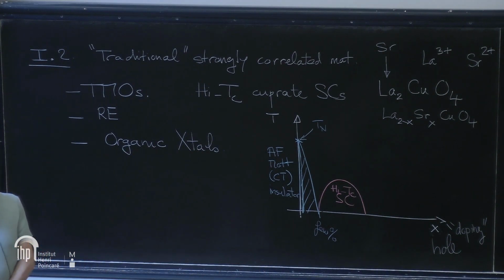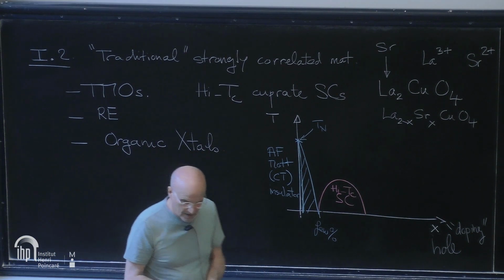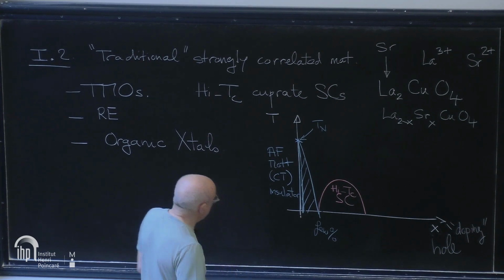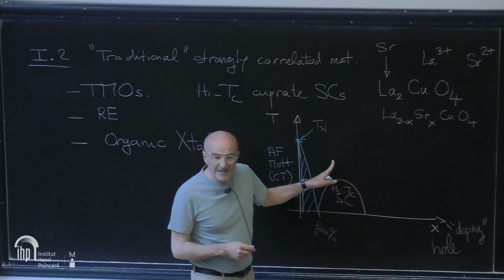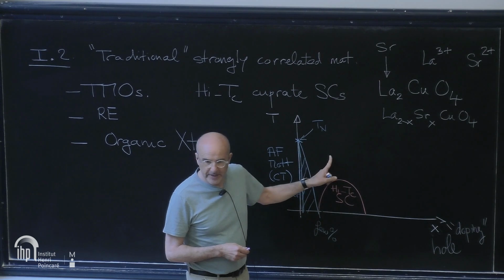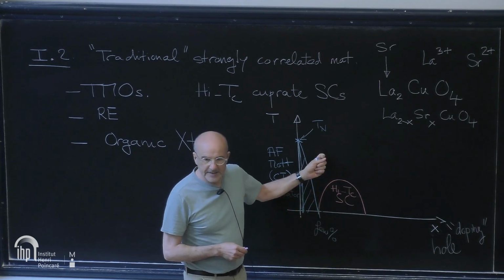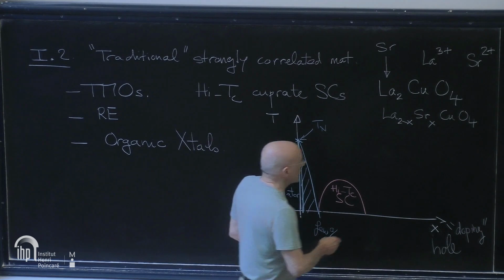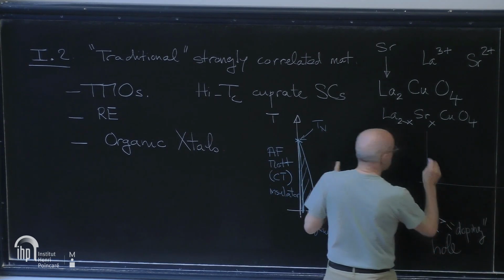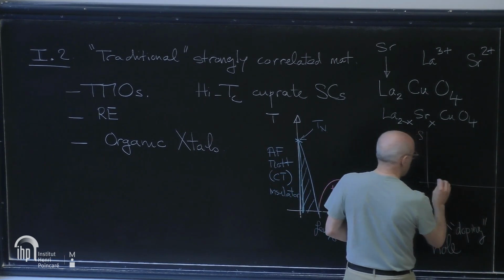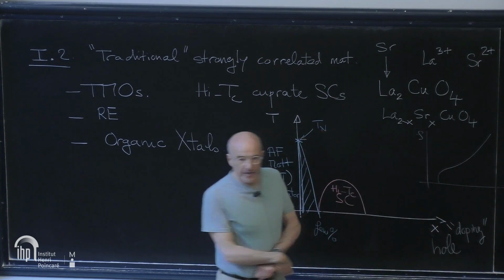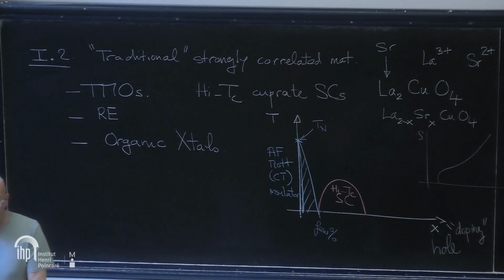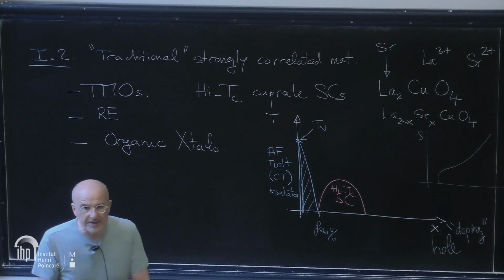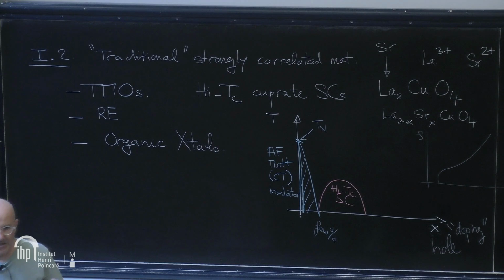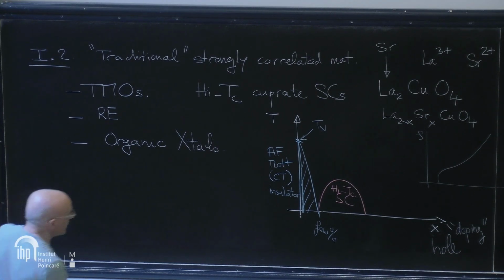But then there are many other interesting phenomena in this system. One of the interesting phenomena is that if I now look at the metallic state here, because with doping the insulator becomes a superconductor, this state is a metallic state. By metallic state, I mean that if we measure resistivity in this state, resistivity versus temperature is going to be increasing with temperature, right? dρ/dT positive. The more we heat up the system, the more resistive it is. That is kind of a definition of metallic behavior.